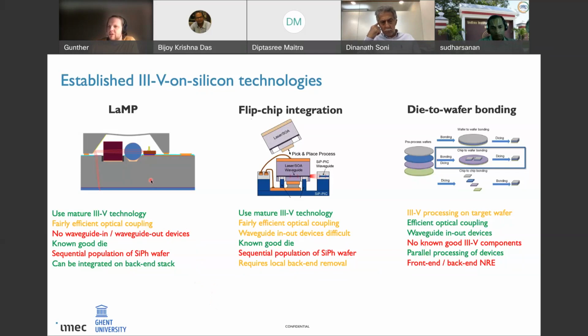Now, what is good about, let's say, the more classical hybrid integration approaches, such as the micro-packaged laser and flip chip integration, is that you have this known good die concept. You can test your III-V component up front and then integrate it on your silicon photonics target wafer. And that will then result in a higher compound yield of the photonic IC. Now, a die-to-wafer bonding approach does not have this known good die concept. So you only know whether the integration was successful after you have fabricated the entire chip and characterized the laser. So this kind of die-to-wafer bonding approach can result in a lower compound yield.